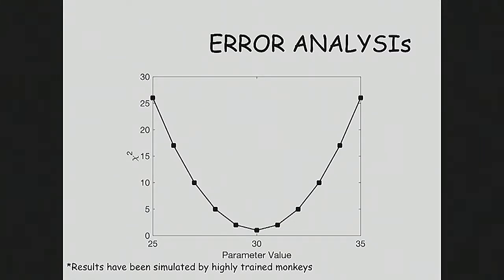But when you go to something like the Pedersen model, where you have a bunch of parameters, the estimated error returned to you from that fit is going to be artificially small and potentially inaccurate. So here we're just going to quickly go over error analysis as described by Venki, the beamline scientist. What you want to do is generate a chi-square distribution for a given parameter. So you set that parameter at a bunch of different values, let everything else vary, and look at how your chi-squared varies. We didn't actually have time to do this for our data, so I've simulated these results shown here.